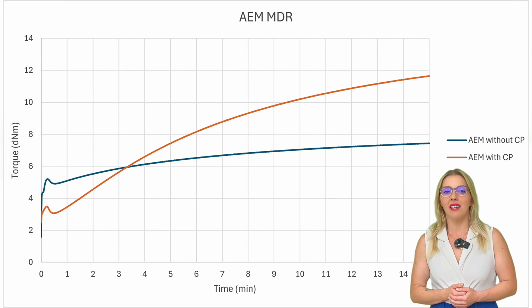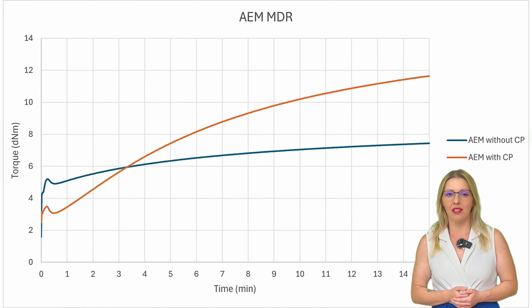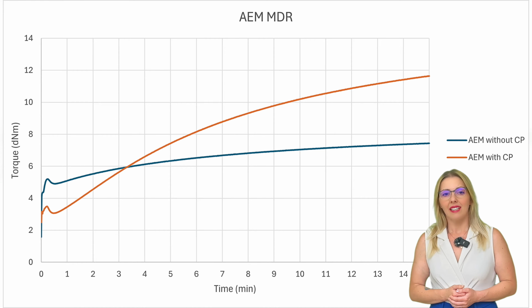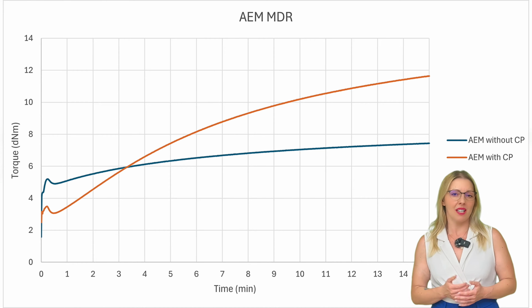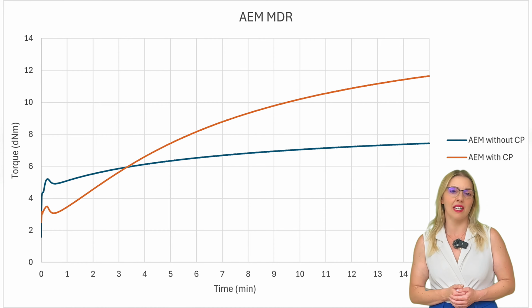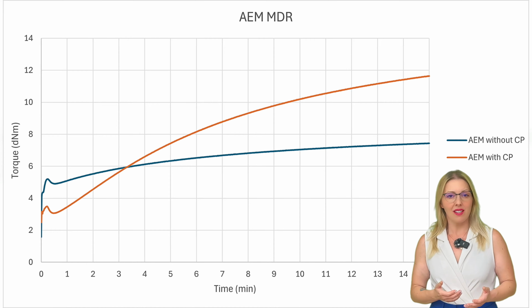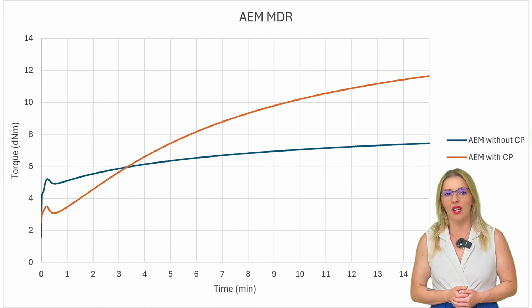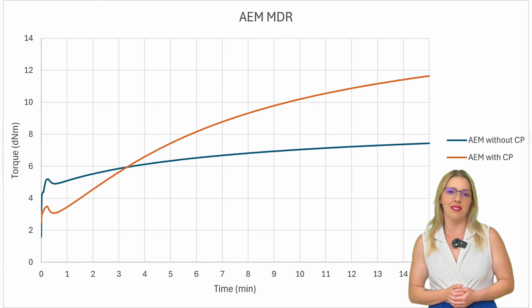Now here we see the AEM compound. Again, the blue line shows the decrosslinked material without added curative. Interestingly, there's a moderate increase in torque even in this state. That is because peroxide-cured compounds can retain some unreacted peroxide or coagents after the first vulcanization cycle. So we are seeing residual curing behavior here, which is not unusual for a peroxide system.